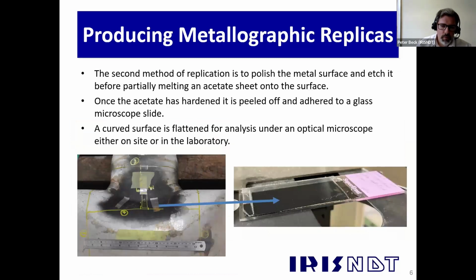And then the one that we typically use is this one with the acetate sheet. The way that we would generally do this is we would prepare the metal surface, polish it to a 1 micron finish, and etch the surface. Obviously, that would depend on what type of metal, steel, stainless steel, aluminium, any metal we can etch really, so the etchants will depend on the metal itself. Then we would apply this acetate sheet. Basically, you would gradually lay this sheet onto the metal whilst also applying acetone. The acetone has the effect of almost melting the acetate sheet, and this allows it to form to the surface of the metal, if you like.